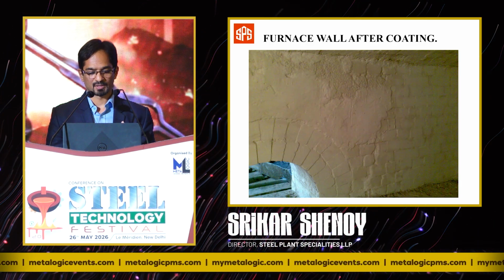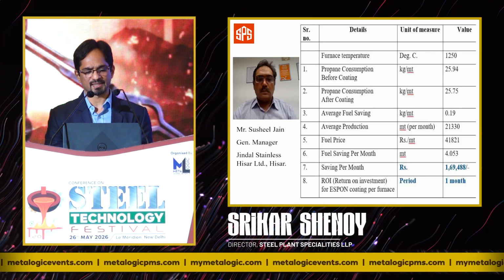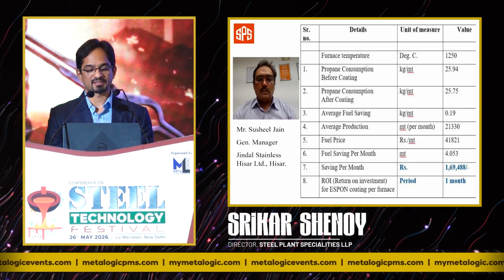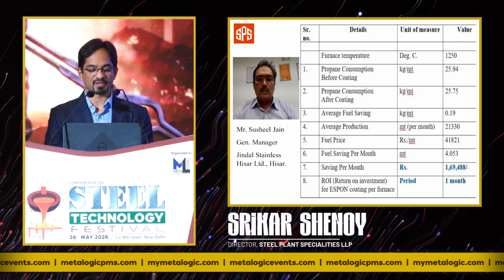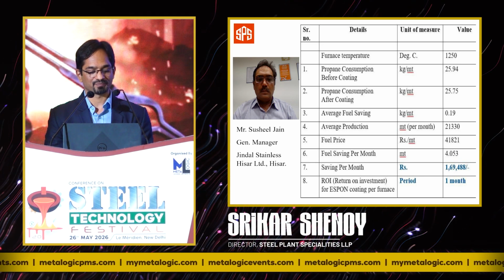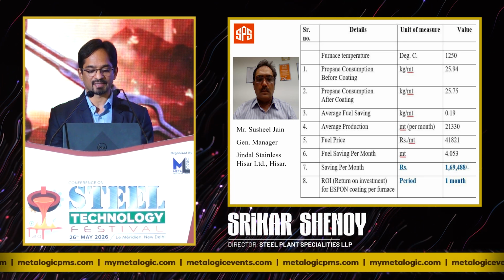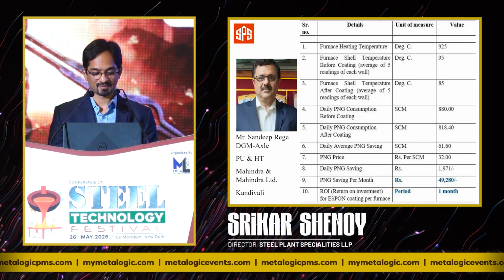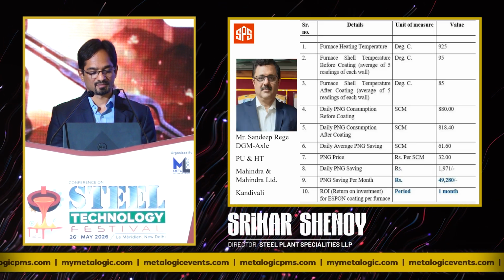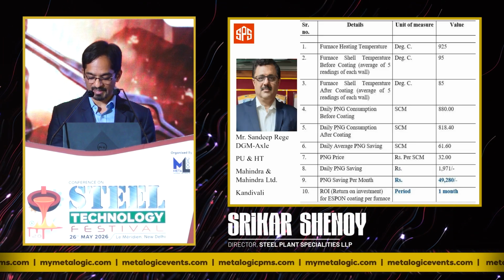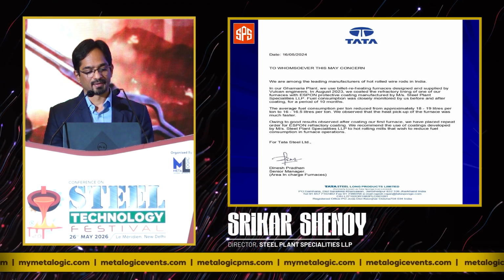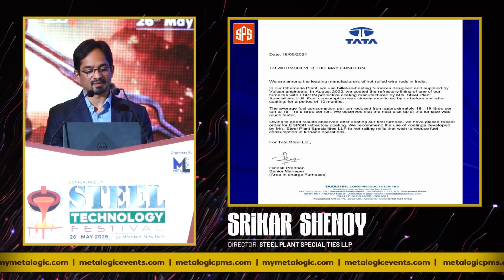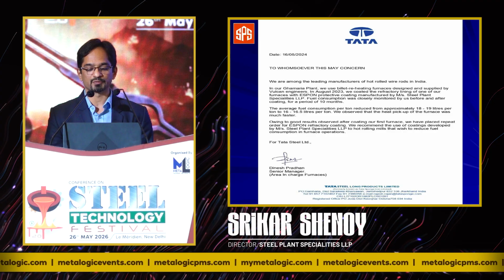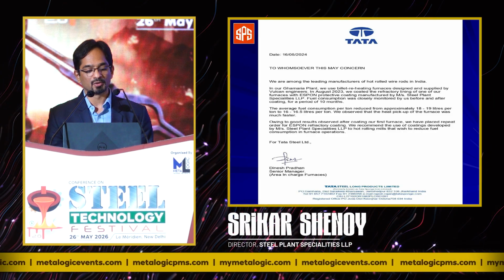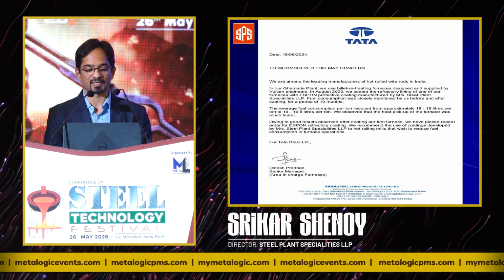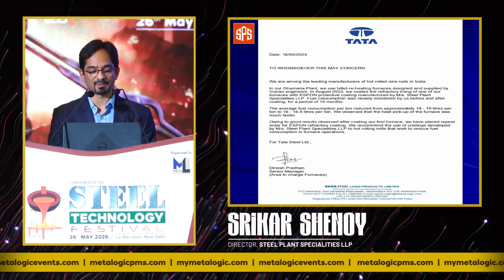Okay. So just a couple of quick case studies here. The furnace outer shell temperature, furnace temperature is 1250 degrees Celsius, and this is at Jindal Stainless Hisar. The return on investment, 1 month. Umpteen such case studies. This one is from Mahindra & Mahindra. A recommendation from Tata Steel stating that the average fuel consumption per ton reduced from 18 to 19 liters per ton to 16 to 16.5 liters per ton, and faster heat up time of the furnace.